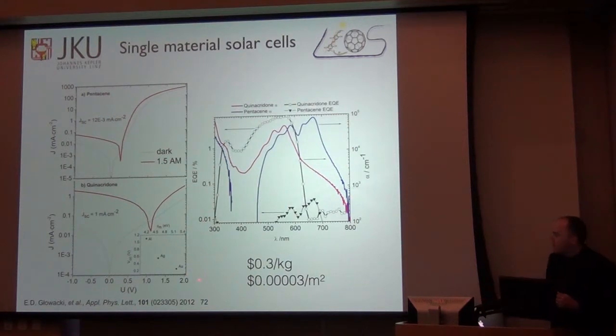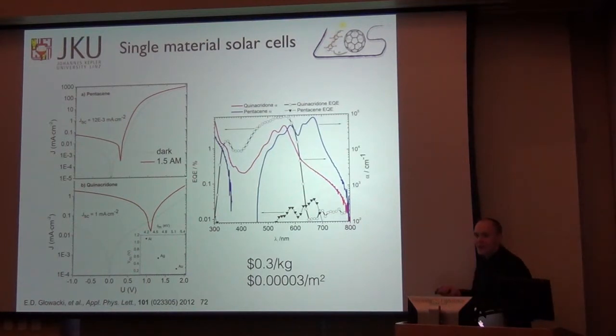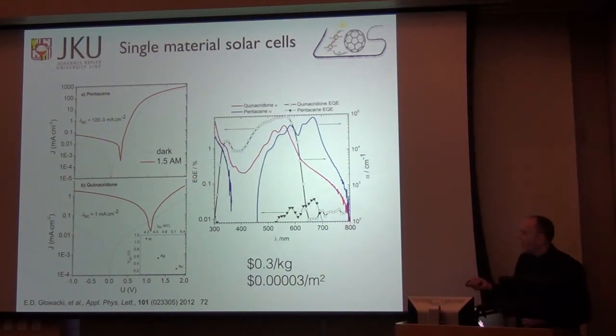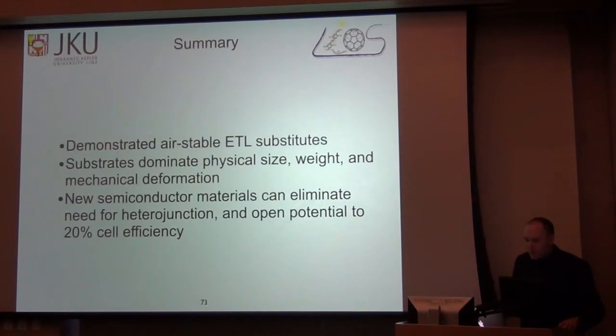And by varying the metal, here we used only gold, silver, and aluminum, we can tune the VOC of this device up to well over a volt, which is very, very high for an organic photovoltaic device, and we have no heterojunction. So to summarize, we've demonstrated an air-stable electron transport layer.